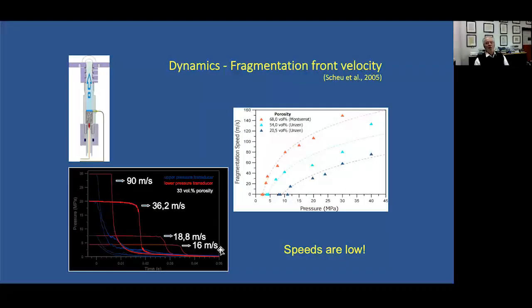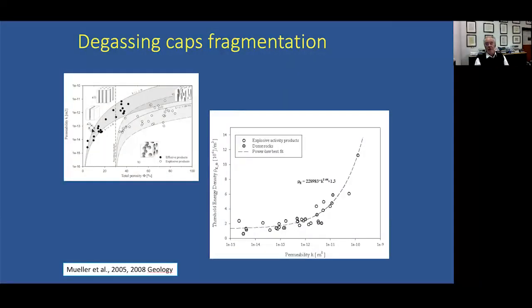These velocities are obtained by measuring the dynamic pressure above the intact sample and measuring the dynamic pressure below the intact sample. The shock wave, or the decompression wave, the rarefaction front, which comes into the sample, is picked up by the first sensor. The material begins to erode by fragmentation, and when it reaches the second sensor, you get the second decompression at the second sensor. And the time difference between them very simply gives us the speed, the linear approximation to the speed of the propagation of the fragmentation front. So these things are grinding themselves to death.